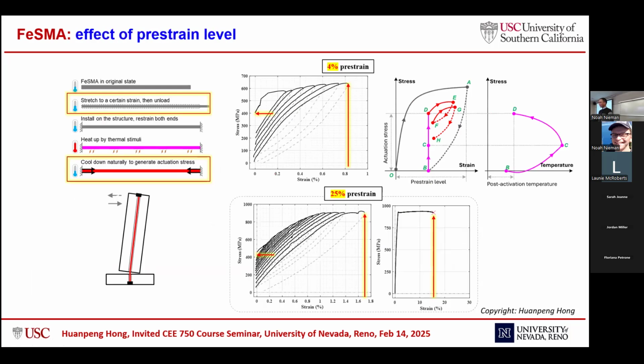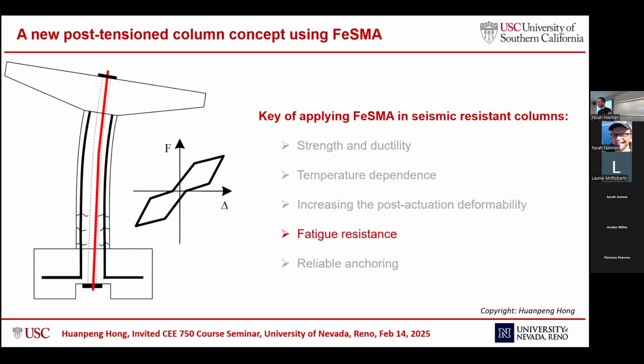And because if we increase the pre-strain levels, we are sacrificing the total deformability of this material, we wanted to ensure increasing the pre-strain level is feasible for practical application. When we increase the pre-strain level from 4% to 25%, of course the strain recovery doubles. This is what we know. But after this, we stretch this material monotonically to failure. We see that this material still exhibits more than 15% of deformability. That means increasing the pre-strain is not only a feasible way, but also a safe way.